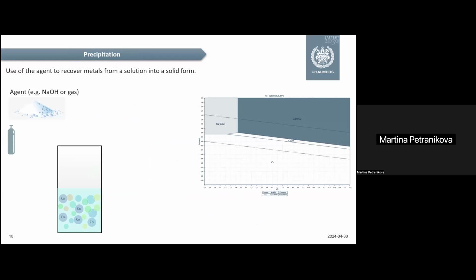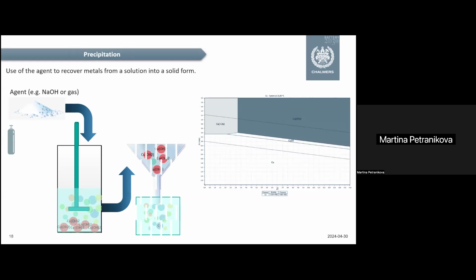Another step which is used in the hydrometallurgical processing very often is the precipitation. And mostly the point is to get this metal from ionic form back to the solid form. So we can use different agents. Very often sodium hydroxide is being used, but also, for example, for copper, it's very often some gas media. And again, we apply this media to the solution where we have our metals, the metal we want to remove precipitates, and then again, we use a simple filtration, and then we can recover or remove this metal.